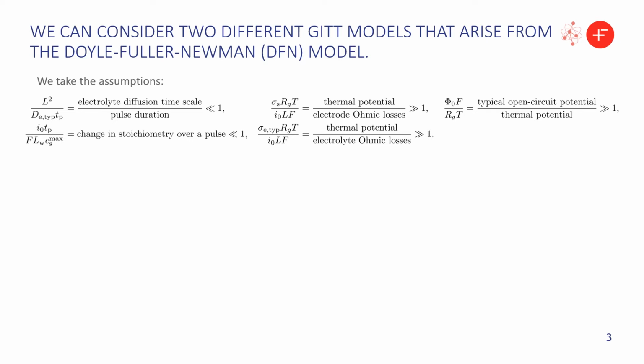So we take the following assumptions. In this case, we assume that the pulse duration is longer than the electrolyte diffusion timescale, so the electrolyte is at the steady state, that the ohmic losses in the electrode and the electrolyte are smaller than the thermal potential, which is the scale where we expect to see variations in the potential, that the open circuit potential variation is much larger than the thermal potential, and finally, that the change in stoichiometry over a single pulse, so how much change in the stoichiometry or the state of charge we make over a pulse, is small. So with all these assumptions, then we can perform this asymptotic analysis.